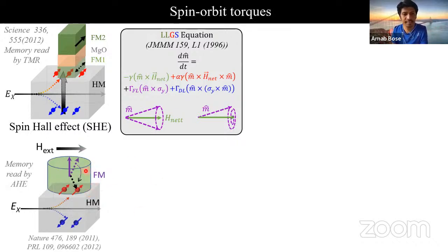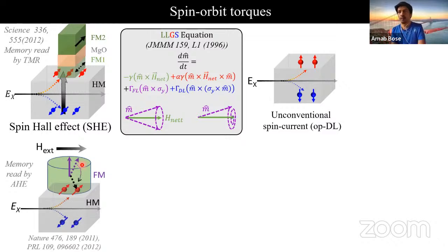But we see that this is not a very ideal situation because we need to apply a symmetry breaking field in most of the cases. However, we would ideally need a material where by applying in-plane current, we can get out-of-plane spins flowing in the out-of-plane direction, which will immediately cause the out-of-plane anti-damping torque on the adjacent PMA magnet. I refer to this as unconventional out-of-plane damping-like torques.